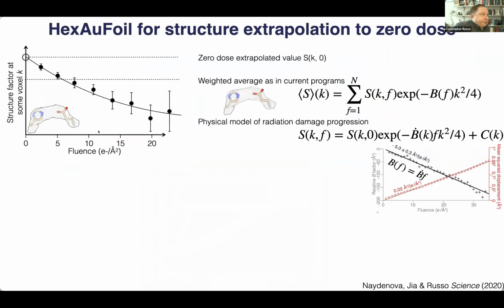So what can we do to do this extrapolation business? Well, the idea is that we take all of the amplitudes and phases measured in the map. And since we have all of them measured at all time points, which is something we never had with crystallography, where this has been done previously, we have both the amplitudes and phases, we can take these structure factors and extrapolate them back to 0 dose. And we do that by a very simple fitting. And instead of taking a dose-weighted average of each one of these frames, which is what's done now, we can actually use all of the information from fitting all of these parameters to figure out the position here at 0 dose as accurately as possible.